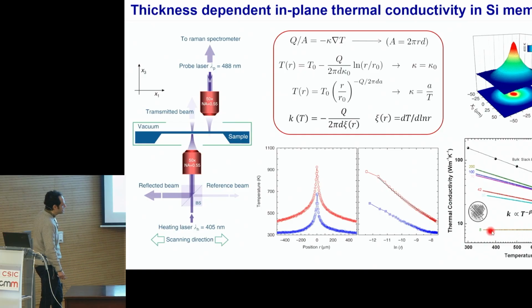So what we found here is by starting from bulk silicon, and when we decrease the thickness, we end up in a silicon membrane with 8 nanometer thickness, and we can reduce the thermal conductivity by more than a factor of 1. Sorry, 1 order of magnitude, sorry. So this means by a factor of 10, yes. So this means that this is an efficient way to decrease the thickness in order to decrease the in-plane thermal conductivity. And this is happening because we decrease the thickness, we increase the phonon boundary scattering, so the thermal conductivity is decreasing.